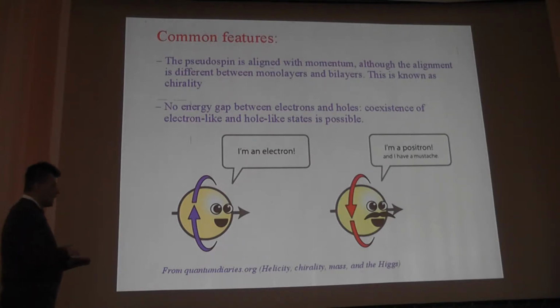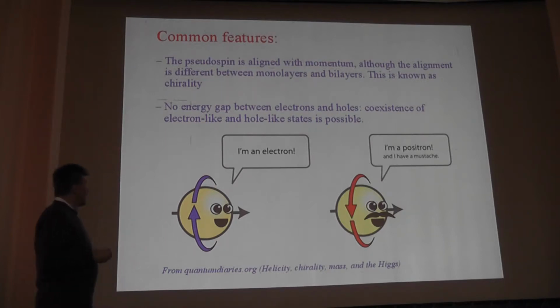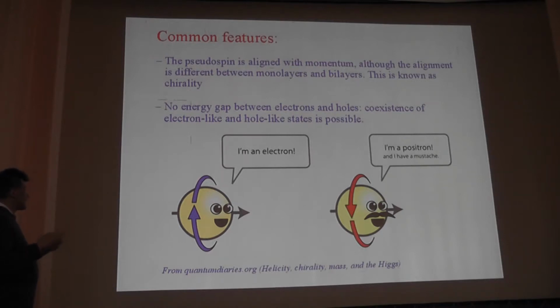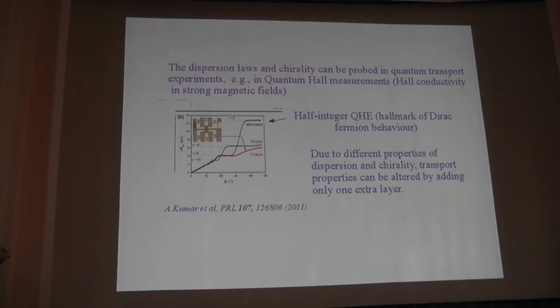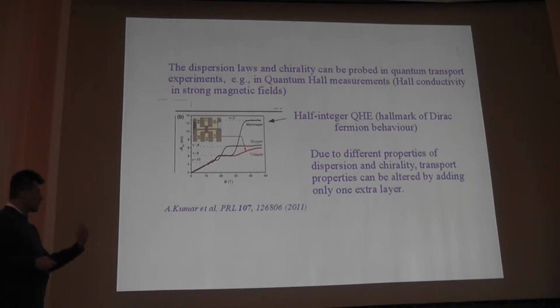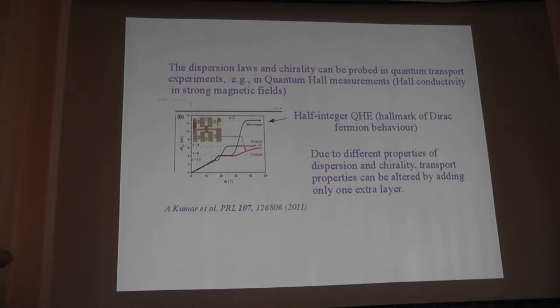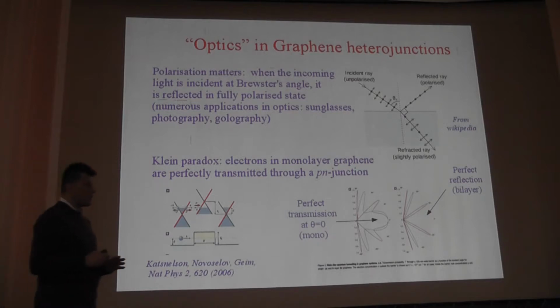The thing which is common to single-layer graphene and bilayer graphene is the chirality of charge carriers. It works slightly differently and is somewhat similar to what happens for relativistic particles. Another thing is that there is no true gap between the electron band and the hole band. This difference can be probed in experiment. Here are measurements of the Hall coefficient of a sample in a strong perpendicular magnetic field. You can notice that the curves for bilayer graphene and monolayer graphene are very different. The experts would recognize here the quantum Hall conductivity. Again, simply adding another layer completely changes the electronic properties of the material, and if you add a third layer, the properties would change again. So now you can ask me some questions.